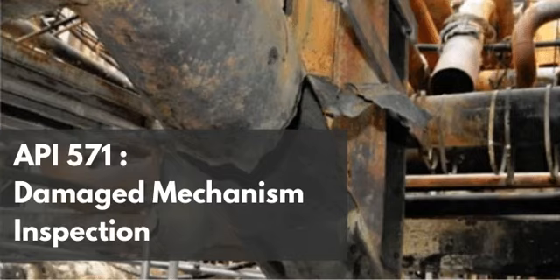Well, it really comes down to the underlying crystallographic structure of the metals. Okay, getting into the deep physics here. Yeah, but it's important. Copper alloys possess a face-centered cubic, or FCC, atomic lattice. And this specific geometry has multiple densely packed slip planes. So under high stress and aggressive chemical attack, the atomic bonds along those slip planes can be physically sheared. Ah, so the crack has a built-in geometrical pathway to just cleave straight through the crystal.